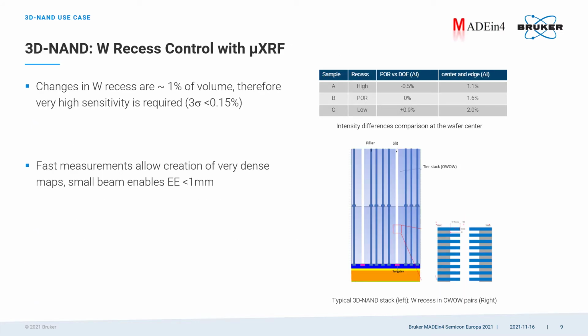This is one example of an XRF application used in memory. XRF is used to control the tungsten recess in 3D NAND structures. On the right-hand side, you see the typical 3D NAND stack with alternating oxide-tungsten pairs. Changes in tungsten recess only make up for about 1% in sample volume, therefore a high sensitivity is required. We could prove that our tool has a 3 sigma relative standard deviation of less than 0.15%. So we are sensitive to the changes in the DOE, but also to variations across the wafer.